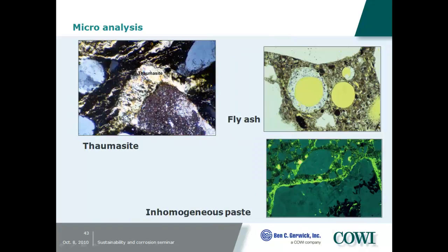We can also look at sulfate attacks. This is a special type of sulfate attack called thaumasite. If you go to where you have very low temperatures and high humidity, thaumasite would precipitate instead of gypsum, and that can completely make your concrete go into solution. Somebody said this looked like a fried egg, and I completely agree. But this is a glass particle from fly ash, and you also have residual carbon, which is also an indication of fly ash being added.